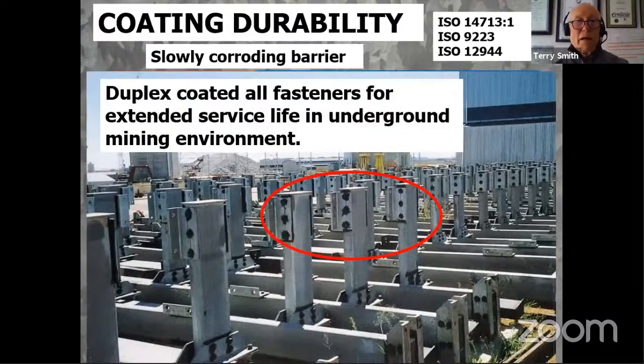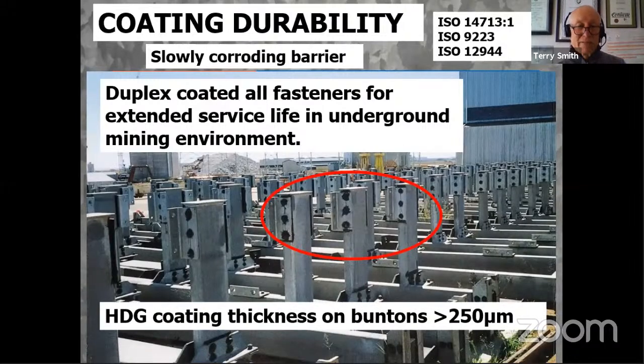You can see some of these, called buntons, which are basically the structural steel holding the vertical steel in an underground mine, which is up to 3.5 kilometers deep. We realized that the fasteners they had used, even though they were hot dip galvanized, had a coating thickness that didn't match the coating thickness on the bunton. So we duplexed all these fasteners and also fixed all the crevices so that there wouldn't be crevice corrosion prior to them being installed in a mine.